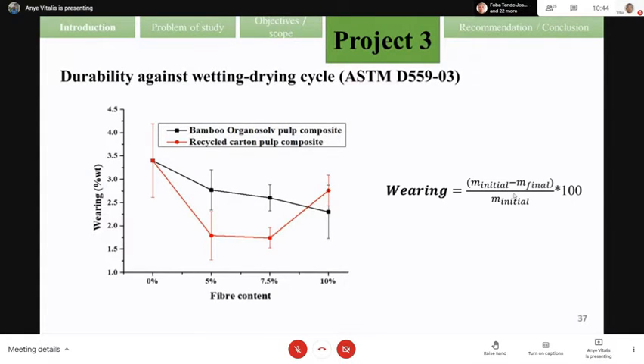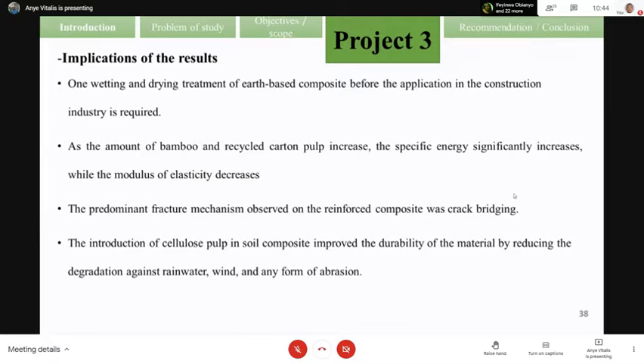After 7.5% of the recycled fiber, there's an increase in the percentage, where we show that after that 7.5, the fibers can form a cluster, which can reduce the adhesion between fiber and matrix. What is the implication of the result?